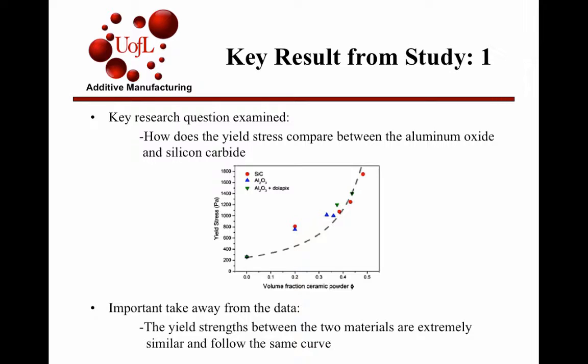They also tested these against colloidal inks, which are what are traditionally used with robocasting, and they didn't put those on the graph, which is a little bit aggravating, but they concluded that these were comparable to the colloidal inks. They were very similar. So the yield strengths between the two materials were very similar. The Dolapix helped the aluminum oxide a little bit, and these were comparable with colloidal inks, which are traditionally used.